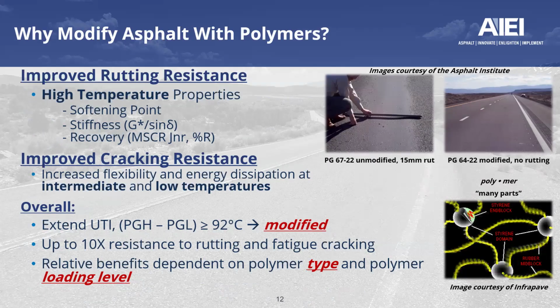The first question that we got to ask to kick off this webinar is why we modify asphalt with polymers. And this stems from two primary advantages. The first one is about improving rutting resistance, and that's at a high temperature by enhancing a lot of the high temperature properties. And then the second will be improving cracking resistance by increasing flexibility and energy dissipation, and that happens at intermediate and low temperature. With polymer modification, we have tendency of extending the useful temperature interval, UTI. However, this is highly dependent on the polymer type as well as the polymer level. It's always been about striking the optimal balance between providing enough stiffness to resist rutting and flexible enough to prevent any type of cracking. Again, polymer modification led to a significant improvement in balancing stability and durability.